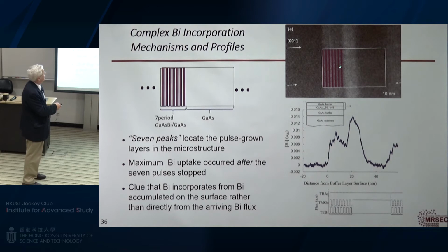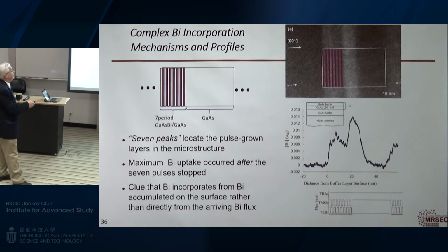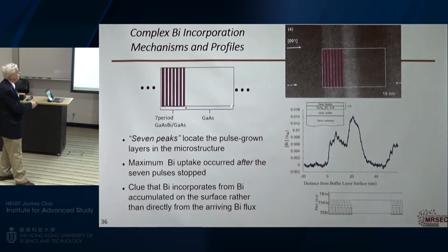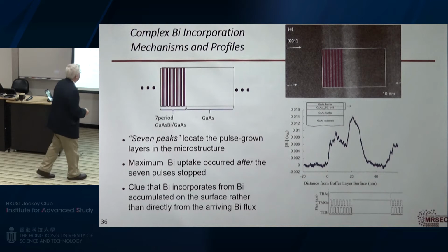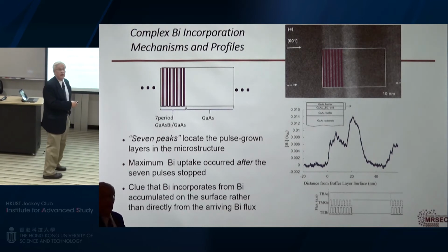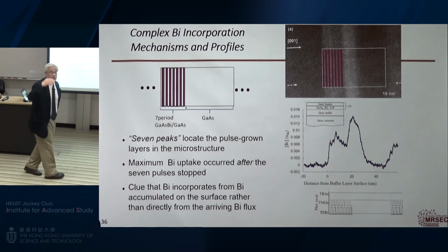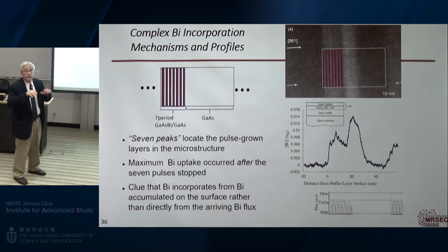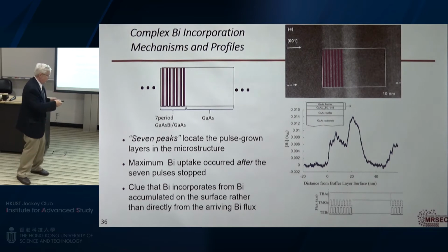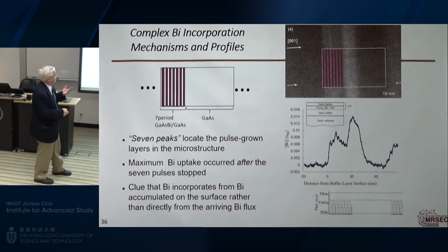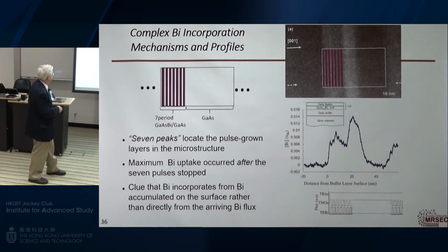This is using transmission electron microscopy. But also when I stop putting bismuth into the system, so there's no trimethyl bismuth flowing into the reactor, all of a sudden I get lots of bismuth into the crystal. The reason for that is because the bismuth actually was riding on the surface as a monolayer, and all the growth was going through that bismuth layer. So the question is, how do I modify that? And then it actually stops growing.